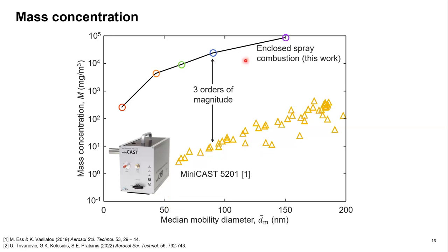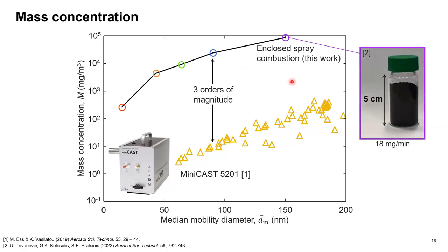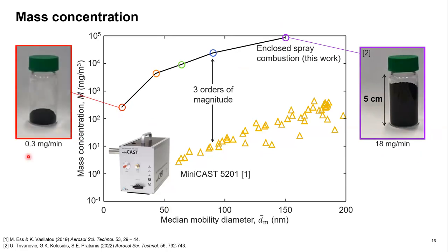At the same time, by enclosing the flame, we are able to prevent oxidation and keep even these small particles from oxidizing away before we are able to sample them. So this allows us at the high end to produce 18 milligrams per minute of soot. So in this case, we can in just a few minutes obtain enough soot for all of the offline characterization we need. And at the low end, this is 0.3 milligrams per minute. So within an hour or maybe two, we still can collect enough soot for our offline measurements.